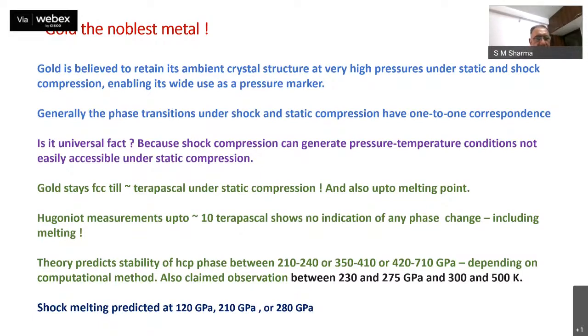The question is, is it universal? Is it a universal fact? I mean, the question which I raised right in the beginning of this lecture: are all the transformations identical? Let's note that, in fact, an issue which was also discussed by Dr. Pandey in one of his talks, that gold stays in its initial structure, face-centered cubic structure, almost to a terapascal. It doesn't undergo any phase transformation up to the highest pressure measured so far, and also stays so up to the melting point. Even if you increase the temperature, it doesn't undergo any structural change.